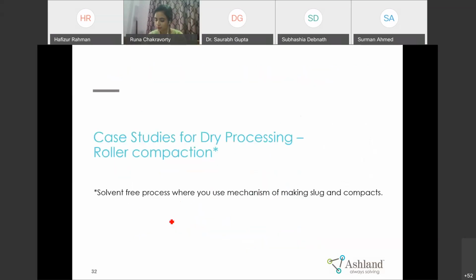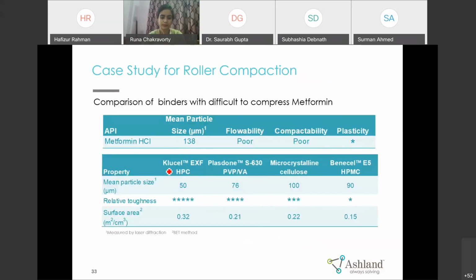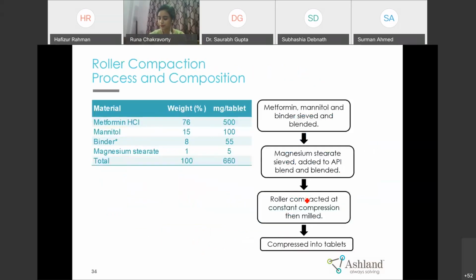Then coming to the next manufacturing process, which is dry granulation. Here, what we have done, we have taken a model API, metformin, which is having poor flow and poor compressibility, and we have taken different binders. We have taken this formula where we have taken 76% of metformin, and we have taken 8% binder. So what we did, we blended metformin with diluent, which is mannitol, and binder, and then after blending, we lubricated it with magnesium stearate and passed it through roller compaction, and after milling, we compressed it into tablets.